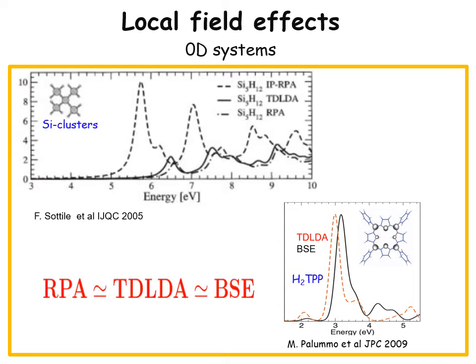It is clear that an even more dramatic effect of local fields can be expected for zero-dimensional materials. For a small silicon cluster, there is again a huge reduction of the intensity and a blue shift of the spectrum when moving from independent particles to the case where local field effects are included, which is named here the RPA approximation. Moreover, doing an RPA or a TDLDA calculation for a cluster, the two curves are quite similar, which clearly suggests how the inclusion of local field effects is really playing the major role with respect to the introduction of the short-range exchange-correlation function of the LDA approximation, and is really essential to obtain reasonably good agreement with experimental data or with more refined, accurate calculations based on the Bethe-Salpeter equation.